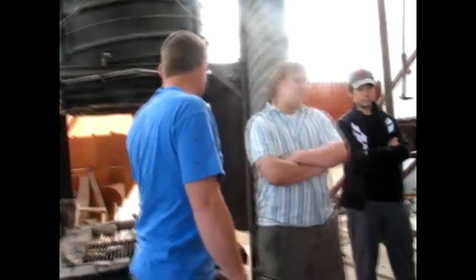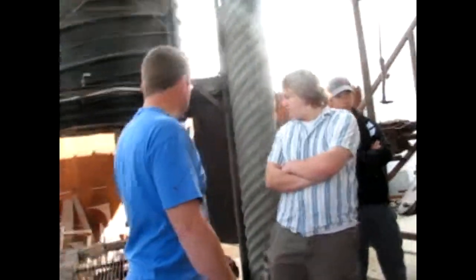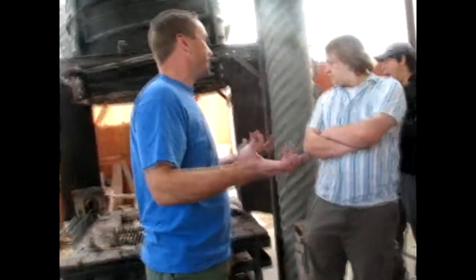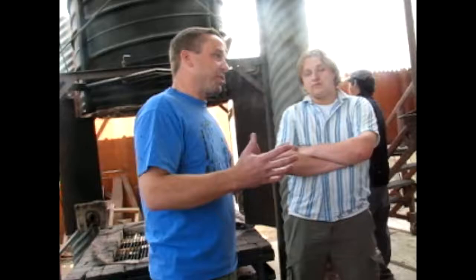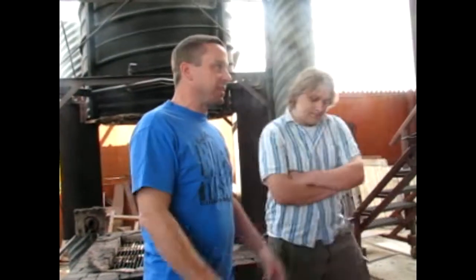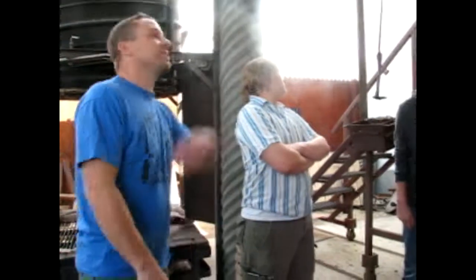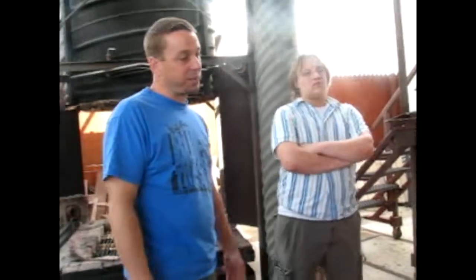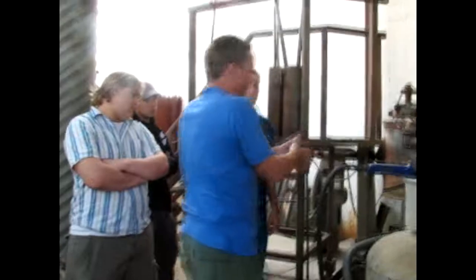And the shells are the same way. They can go up quite a bit, and they get stronger and plastic, obviously, when they're at their temperature. But if you take them past a certain point, they lose a lot of strength, and you have problems again. You pour them, and then you have to start all over, make another wax. We still have occasionally someone will be moving the shell and just clip it on the edge of the steel and put it in there, and then you fill it up and it just fails.